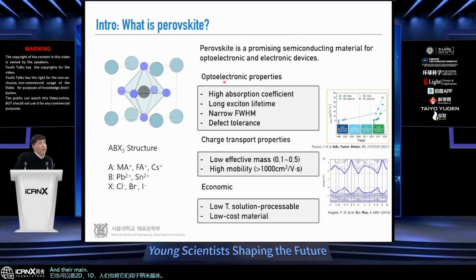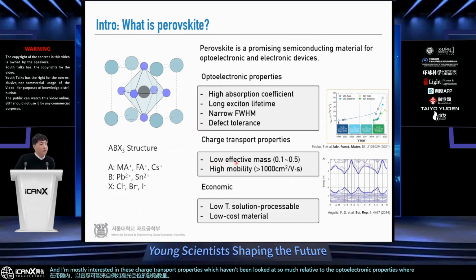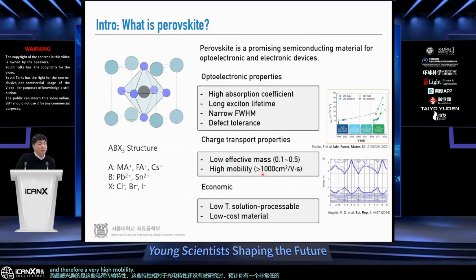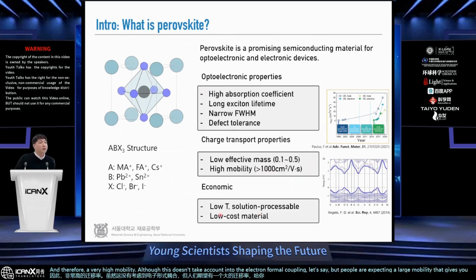Their main interesting properties lie in optoelectronic as well as the charge transport properties, where their bonding is such that you are defect tolerant, and therefore you're not creating states within the bandgap to tolerate the number of defects that you could have from, for example, halide vacancies. And I'm mostly interested in these charge transport properties, which haven't been looked at so much relative to the optoelectronic properties, where it is expected that you have a very low effective mass for these materials, and therefore a very high mobility. Although this doesn't take into account the electron-phonon coupling, people are expecting a large mobility that gives you a high device performance. And not to forget, these are also low energy processable materials.